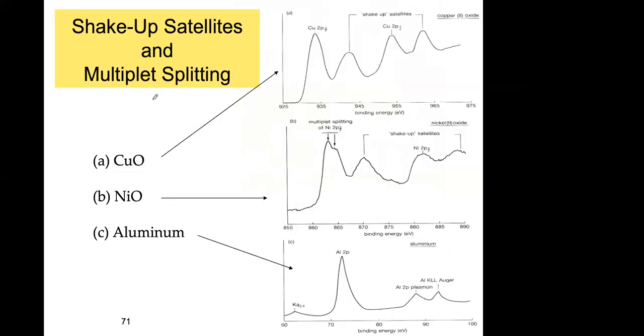So here's an example of shake-up transitions and multiplet splitting. This is copper 2, and copper 2 has very unique satellite peaks, shake-up peaks for copper 2p 3/2 and copper 2p 1/2.